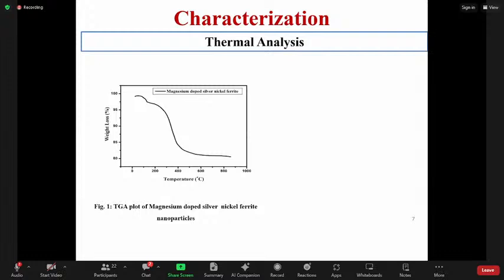From that, at the first stage, there is removal of water molecules at 30 to 150 degrees Celsius. After that, some inorganic materials get removed at 150 to 350 degrees Celsius. After that, from 350 up to 600 degrees Celsius, or up to 500 degrees Celsius, there is a removal of excess ammonia. Why ammonia? Because I have added it in the synthesis for my pH. So it got removed and I got the thermal stability, that is up to 83%. So this is the thermal analysis.